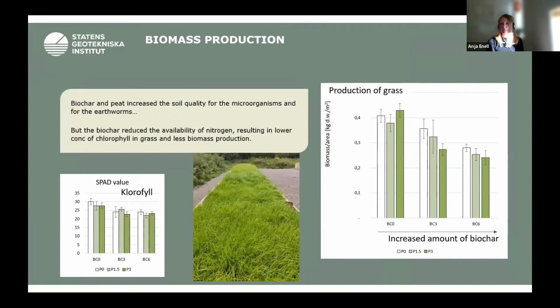And if we go to results from the biomass production, we had expected to have an increased production with the addition of biochar, but we received the opposite pattern, as you can see in this graph here. So on the y-axis, you have the biomass in kilogram per square meter, and it goes down when we add biochar. And this was because the availability of nitrogen in the soil water was reduced. For this treatment, we had chosen a biochar that has a really good absorption affinity for both organic contaminants and metals. So this also resulted in a very good absorption of nitrogen.